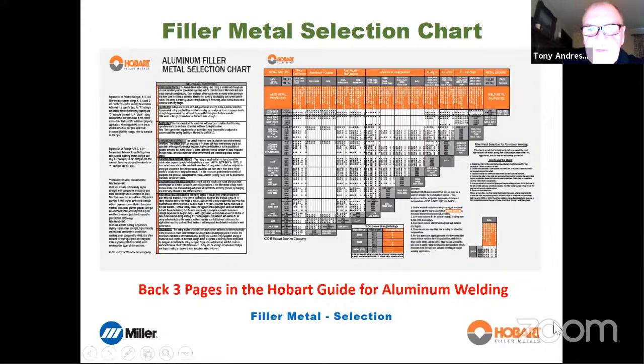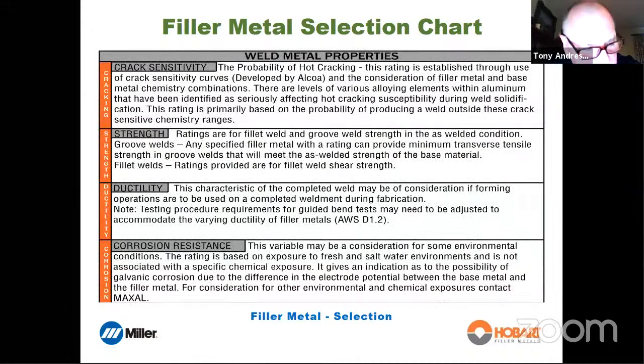Let's just go through and explain how this works. I said earlier, and I'll just reconfirm, that the selection of filler alloy for aluminum is different than steel. And just to give you an idea of what I'm talking about, these are the considerations. Crack sensitivity is really important. Certain alloys are very crack sensitive, and if you don't use the right filler alloy, they will crack. Strength of the filler alloys is significantly different in some instances. You might be able to use that filler for that base material, but the strength could be quite substantially different. And if you choose the wrong one, you might not pass the transverse tensile test.